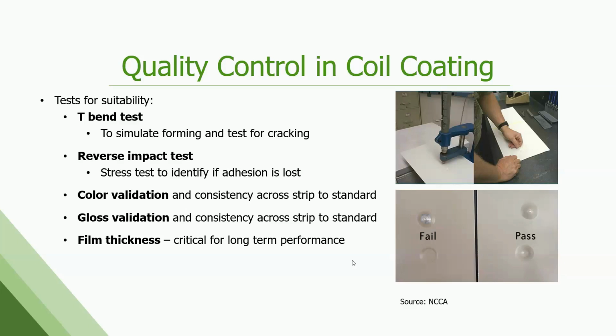So we are applying film between 0.7 and 0.8 mils consistently, with tight color control, usually within a delta E, which is a measurement of color, of 1 unit or less, much less, which is not anything the human eye can pick up on. It is all, for the most part, computer controlled for color as well. It's numerically controlled. Gloss, kind of how shiny that surface is, that's also tightly controlled and measured on every coil. And of course, film thickness. Very critical for long-term performance. If we're not at the right film thickness, it's not going to perform out on the building the way it should, and that impacts warranty. So we have several different methods for checking that film and making sure it's consistent across the width of the coil and from end to end in a coil and from coil to coil.